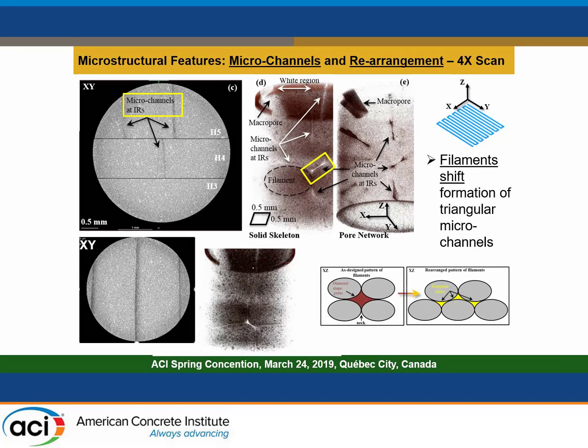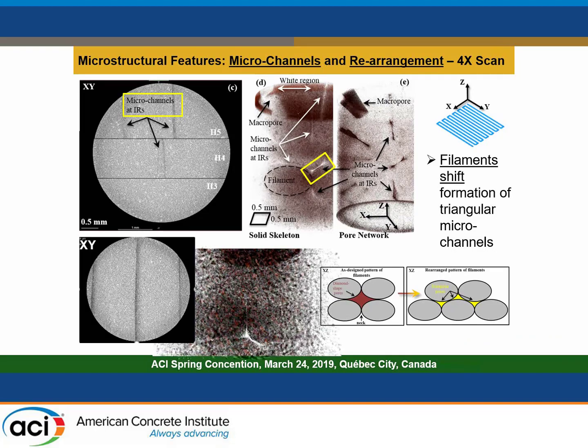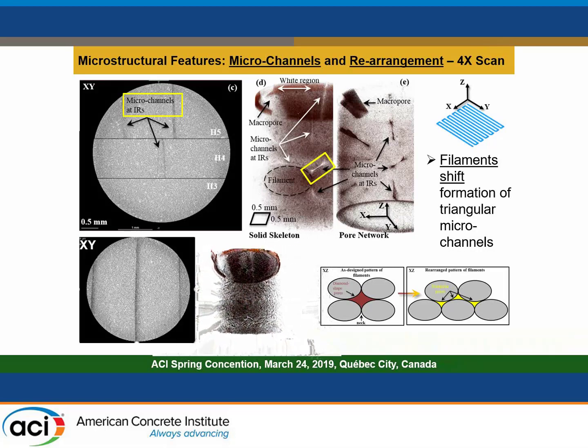We printed cubes that were about 1 inch by 1 inch by 1 inch, and from the outside they looked pretty good, but when we look inside, we definitely saw this shifting. So it's related to both forces, the gravity, but also changing rheological properties with time.